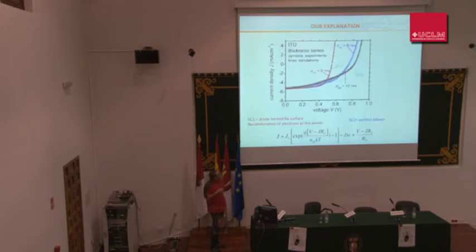So what we propose is that you have two kinds of solar cell in one. One is a perfect bilayer, which is far away from the electrode, and another one which is midway between a perfect bilayer and a bulk heterojunction. And when we did this model, it fits perfectly. The squares are the real data, and the lines are the fitting using this expression, which for those who work on semiconductors is quite classic. This is one diode, and this is the other diode. And then you combine a diode which is limited by surface recombination, so a bilayer. You can fit the 6 nanometer, and if you fit to a perfect bilayer, it doesn't fit. But when you mix both, the bilayer and the bulk heterojunction, you get a perfect fit for any kind of curve you want. So now we really understand how these devices work.